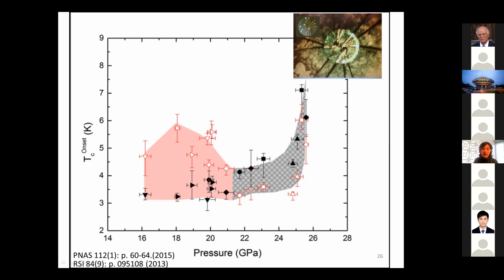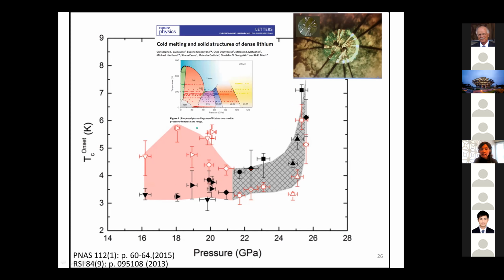So soon after these measurements, we looked at the structural phase boundaries of lithium, and we saw, oh wow, okay, there are a lot of boundaries. The structural boundaries of lithium are very complex, right around 20 GPa. There are lots of different structures. Could it be that these different structures have different boundaries? Because it's unlikely that something like lithium shows non-BCS type of superconductivity. One cannot for sure exclude it.